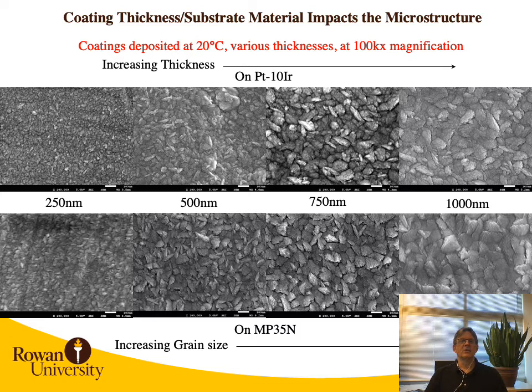On this slide, we're looking at the thickness dependence of the microstructure of the coatings. We have 2 different substrates, platinum 10 iridium in the upper 4 panels, MP35N in the lower 4 panels. The thicknesses range from 250 nanometers to 1,000 nanometers. In general, as you go from thin coatings to thicker coatings, the grain size increases. There are significant differences in the microstructure between the MP35N substrates and the platinum 10 iridium substrates at low thicknesses, and as the thickness increases, those differences seem to go away.